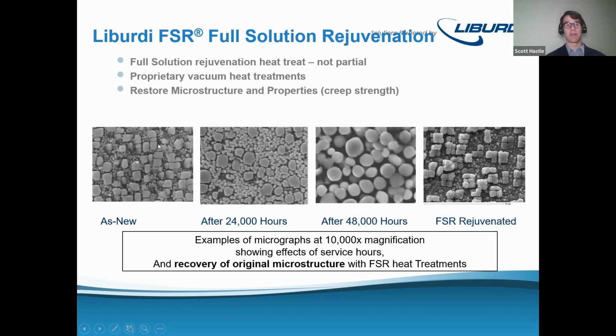But here we have a blocky gamma prime structure. This is the as new. And how do we know the as new condition is we can look at the root of the turbine blade, because that hasn't been exposed to the high temperatures and so won't show signs of aging. And so this structure is what we could expect that the rest of the blade had when it was manufactured. After 24,000 hours in areas on the airfoil, you're going to see some amount of agglomeration. So you're going to see slightly more rounded gamma prime particles, and you're going to start to see agglomeration of these secondary gamma prime particles. After 48,000 hours, you're basically seeing spheres, no sign of the secondary gamma prime particles.